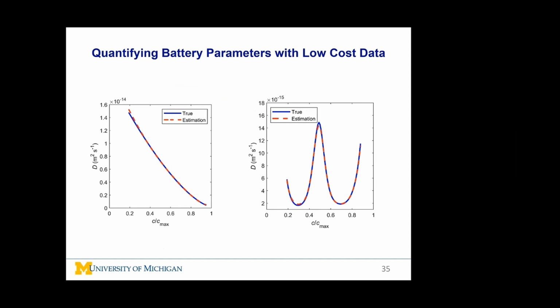Here are some examples. We can show that using this approach, we can estimate the battery diffusivity even if it is a function of concentration C. For the figure on the right, we can observe that even when we have a very complex dependence of diffusivity on concentration, so that it is not a one-to-one mapping - for instance, for different concentrations we can get the same diffusivity - even for such complicated cases, the approach can correctly estimate the battery parameter.